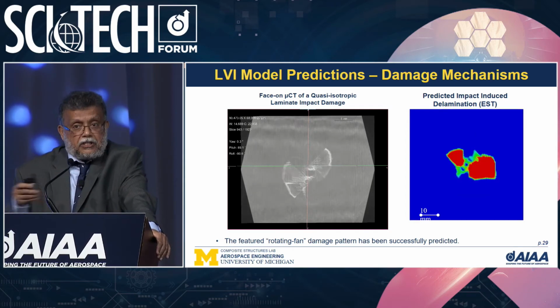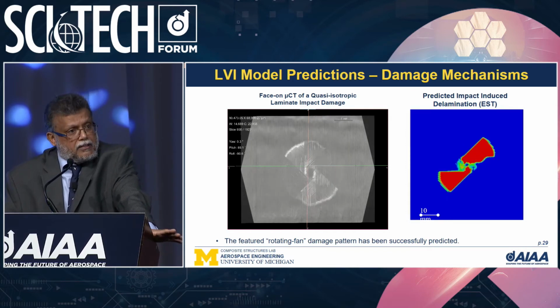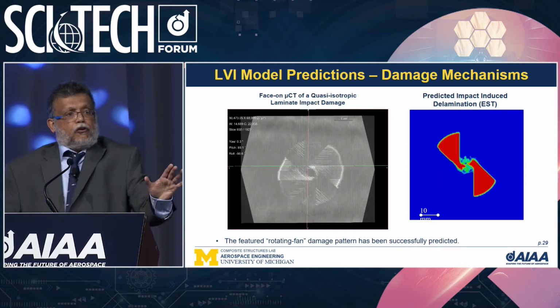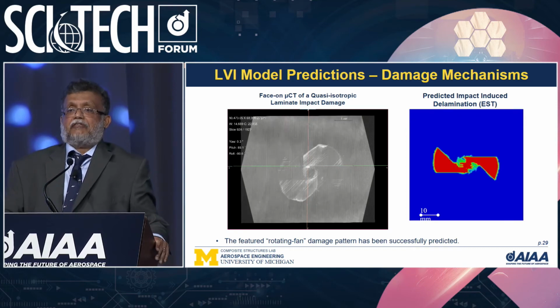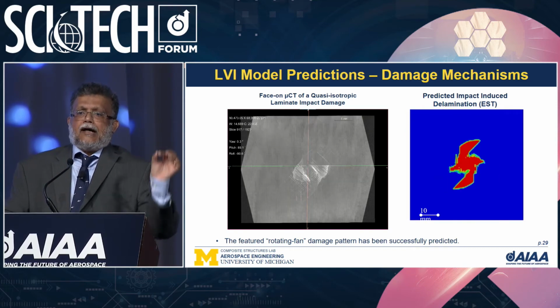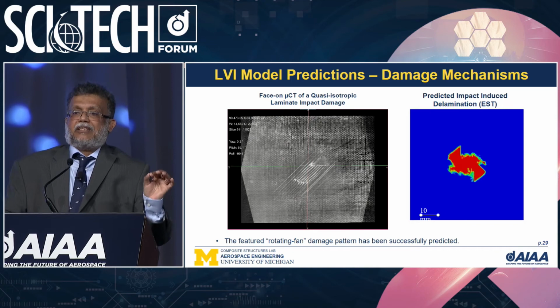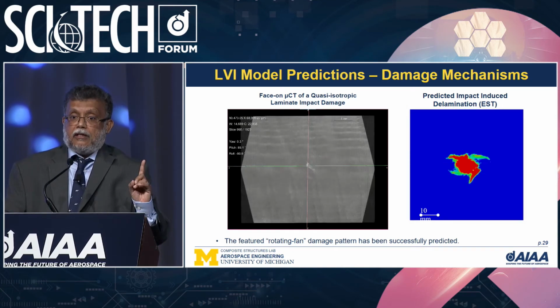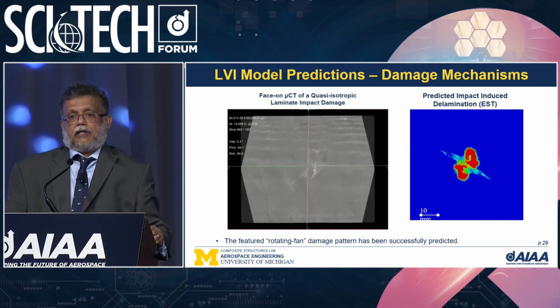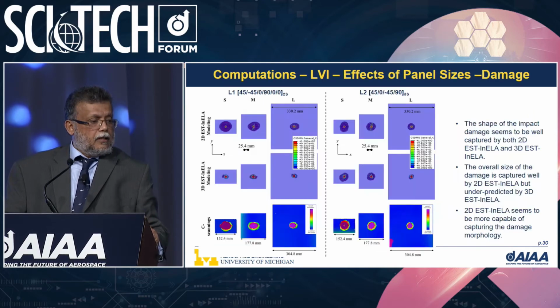So the delamination shapes are captured very well, and the reason I say that is that for the problem of predicting compression after impact, you don't need a high resolution tool to capture each matrix crack. What you need is to capture the delamination patterns correctly, which is what EST does.